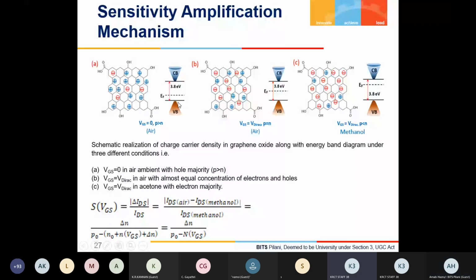This is the Dirac point, when VGS is equal to the Dirac point and the electron and hole concentrations are equal in air ambient. The Fermi level is exactly at the center. And this is the methanol ambient, or reducing ambient, when VGS is fixed at the Dirac point voltage, but due to the injection of a few electrons by surface reaction with methanol, the Fermi level is shifted towards the valence band. So now if we apply the methanol ambient with VGS equal to 0, the shifting of the Fermi level will be very limited, because of the large hole concentration, and some addition of electron concentration will not be so effective.